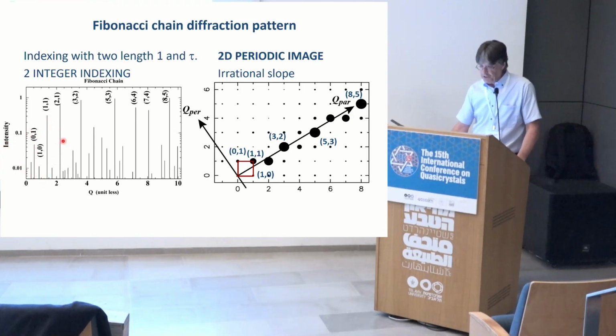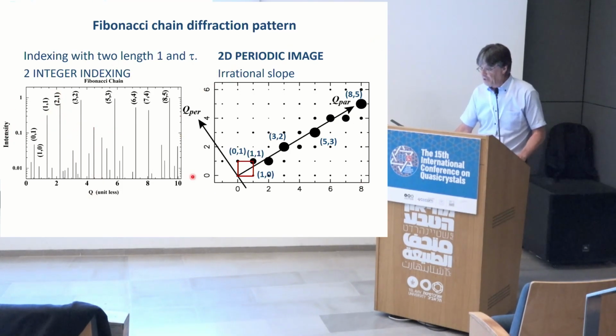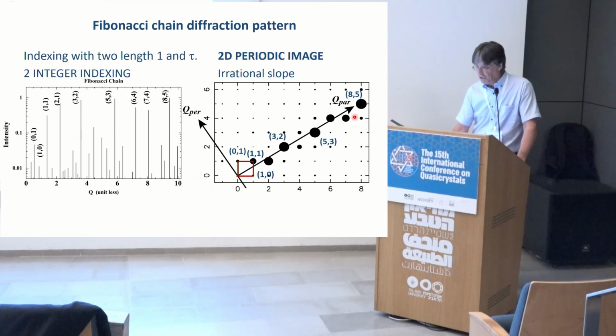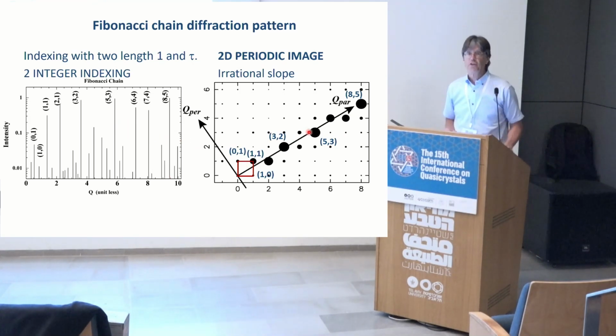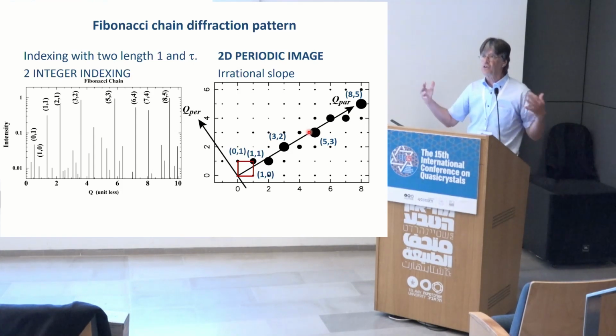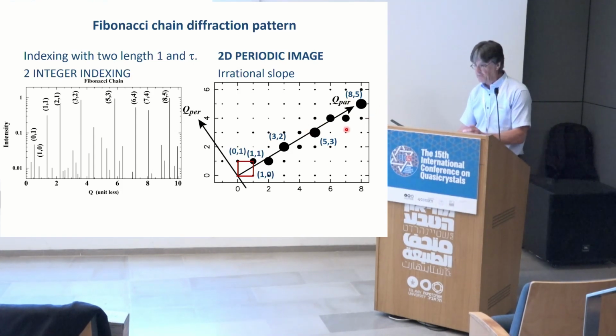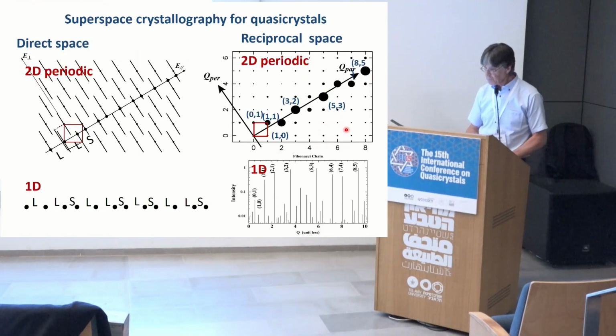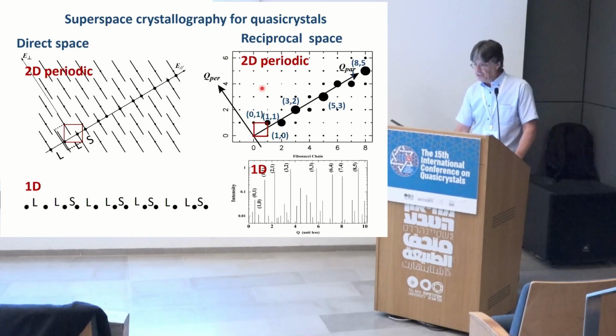The trick, so to speak, the mathematical trick going on to get to this periodic image, is that because you have an indexing with two indices, every Bragg position can be indexed with two integers. You can map this figure into a periodic map, which is shown here. So it's exactly the same. You find this 1,1, which is here. The 3,2 is here. The 5,3 is here. So there is just a one-to-one correspondence, and you go from something that does not look periodic to something which is periodic, but with an extra dimension. And the trick is really to use this periodic description to describe the structure of your quasicrystals.